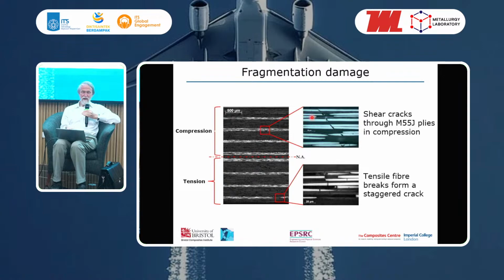And if you look at the micrographs, you can also see how different the damage is on the tension and the compression side. So on the tension side, we see these breaks in the fibers which are perpendicular to the fiber direction. Whereas on the compression side, we see what look like shear cracks through the fibers at an angle of about 45 degrees. Now these look like shear cracks, but actually this is not what's happening.